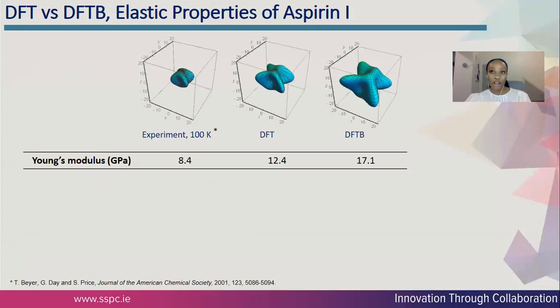The 3D spherical plots shown here represent the Young's modulus of aspirin 1. And the values in the table here give the average value of the Young's modulus in gigapascals. What is apparent is that the two computational methods overestimate the Young's modulus as a result of missing temperature effects, with DFT unsurprisingly being close to experiment. Overall, though, the two computational methods capture the Young's modulus well qualitatively.